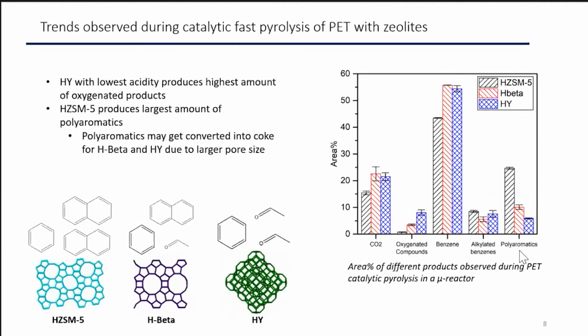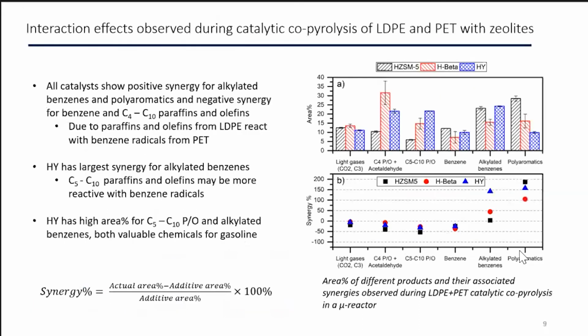We also see that the polyaromatics are highest for HZSM-5. And why we believe that this is the case is because these polyaromatics are coke precursors. And we believe for the H beta and HY catalysts, what would be a polyaromatic is actually staying inside of the catalyst as it is being converted into coke. And this correlates with what we saw in our TGA results, that the H beta and HY had the highest solid residual.